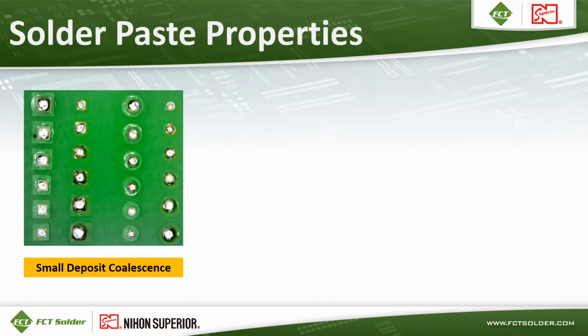Small deposit coalescence is becoming more important as we go to more smaller solder joints and microscopic components. With this particular diagram, this is a graping test that we like to run. When I say small deposit coalescence, I want to make sure that the solder powder reflows completely and forms a smooth, contiguous solder joint, and not have individual solder powder particles sitting there like a bunch of grapes that could potentially have a weakness in it and crack and fail.